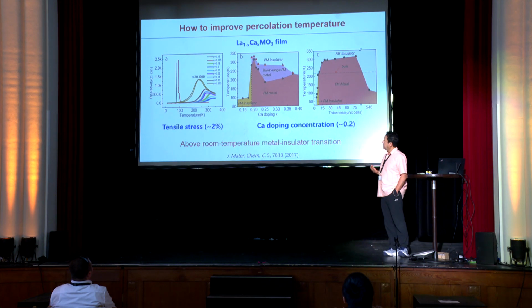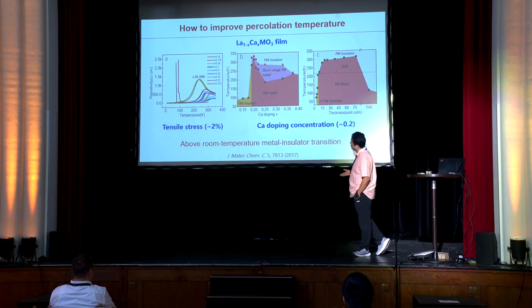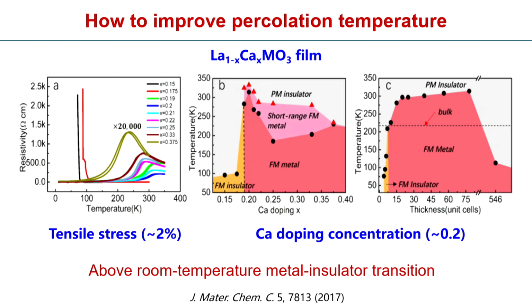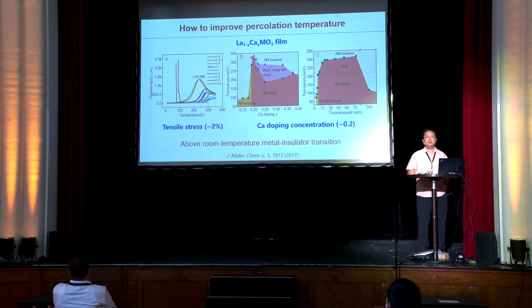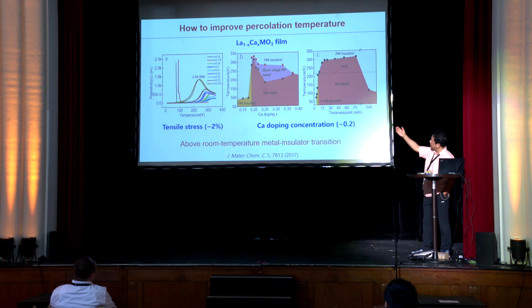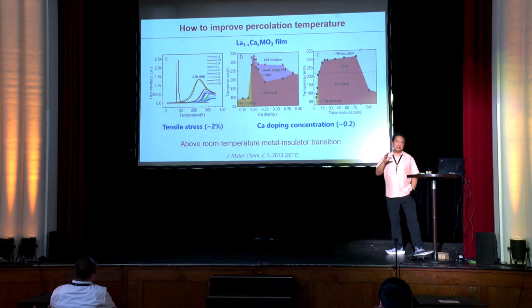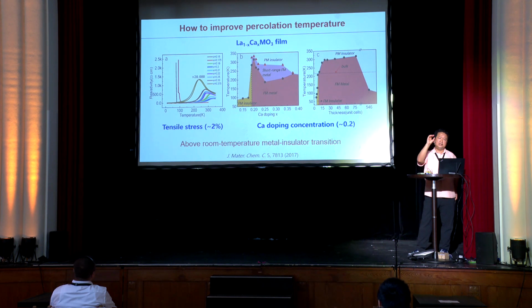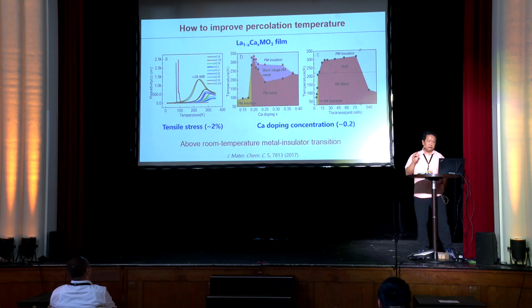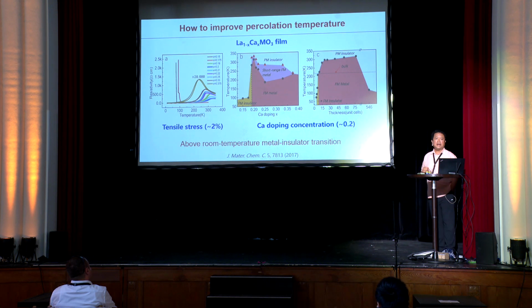Now, what about this temperature? We find that we grow these LCMO films on a tensile strain substrate. In this case, it's an STO substrate, right? So you can see this is the final result. Just looking at certain doping concentrations, you can see under tensile strain, the LCMO film, the bulk Curie temperature is about 220 K or so, right? But this LCMO film's real Curie temperature becomes over room temperature. So we also understand that from the band structure, it is because the tensile strain leads to a very increased vertical coupling, exchange coupling. Of course, the lateral coupling becomes reduced, but the vertical coupling is enhanced, and that gives you a larger TC in this case.